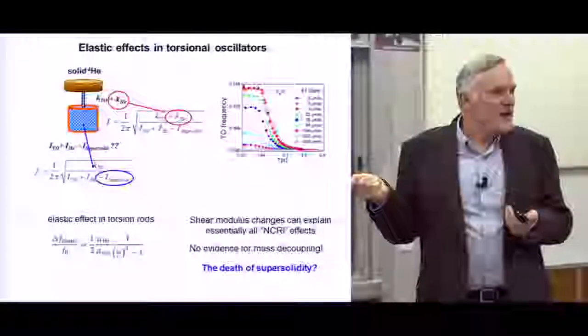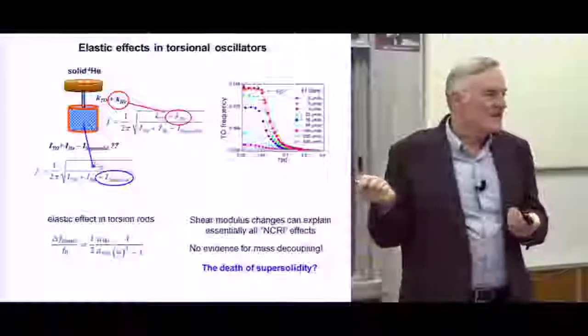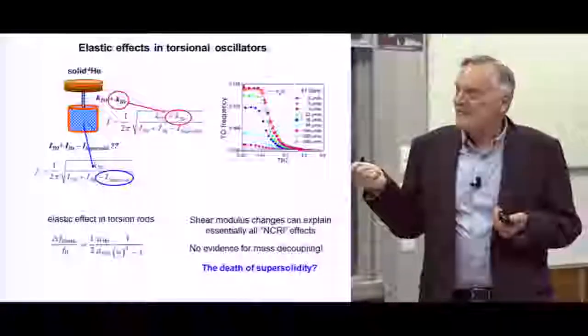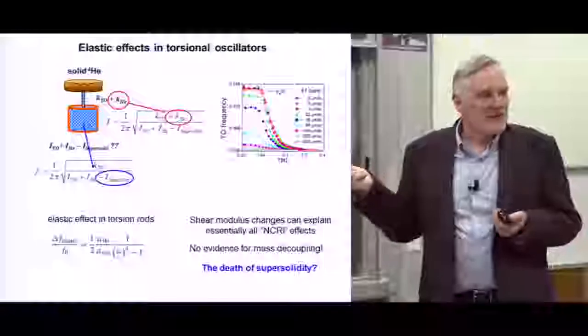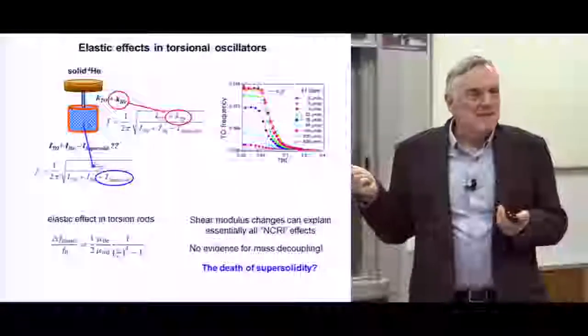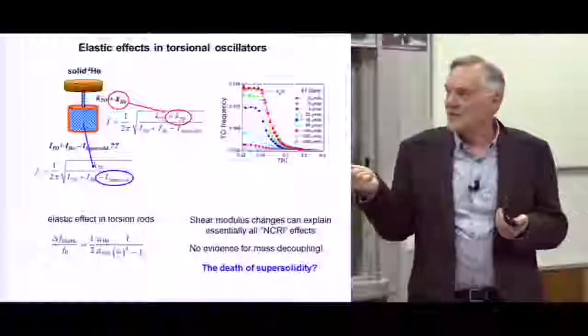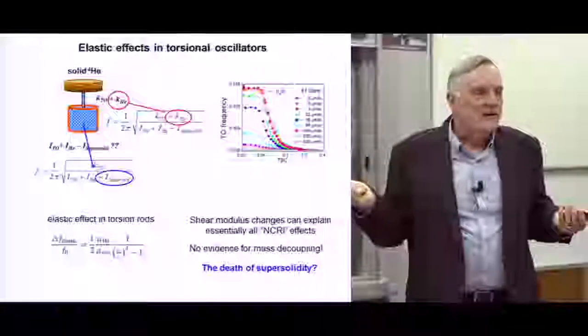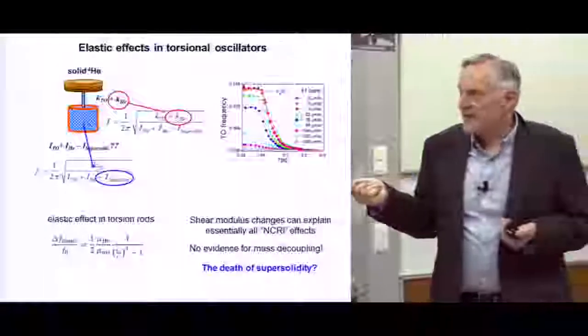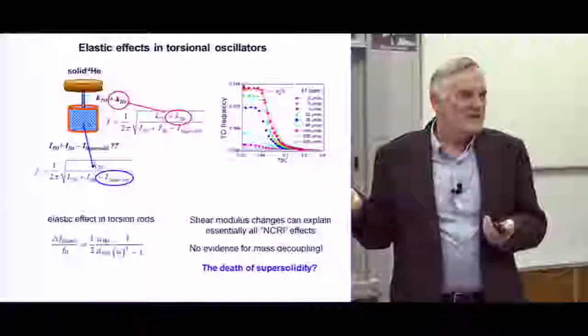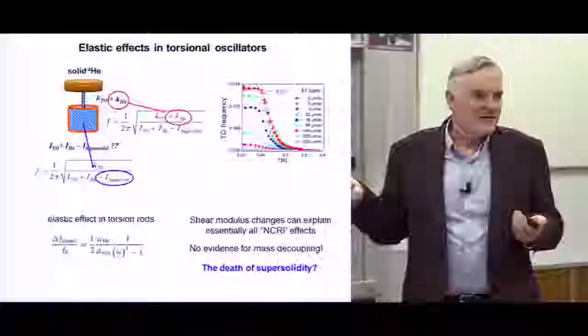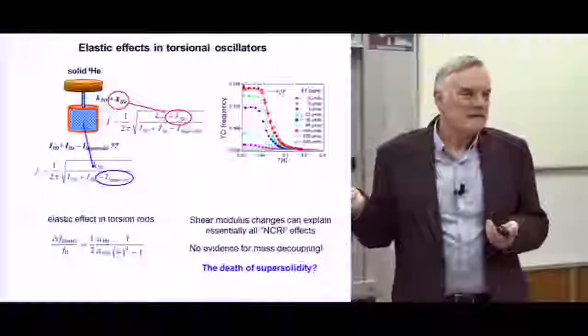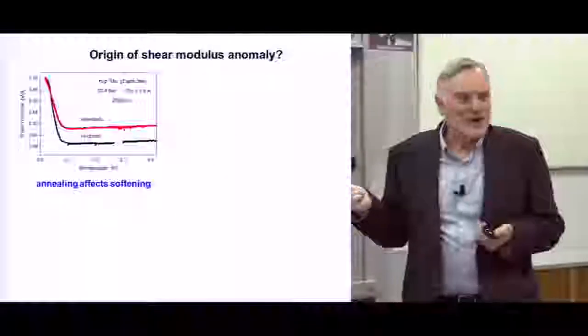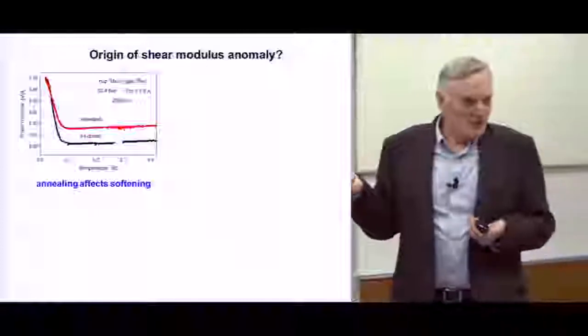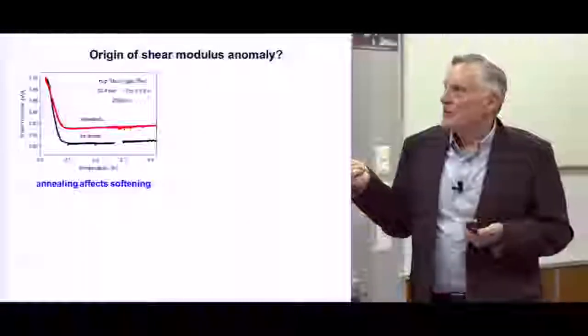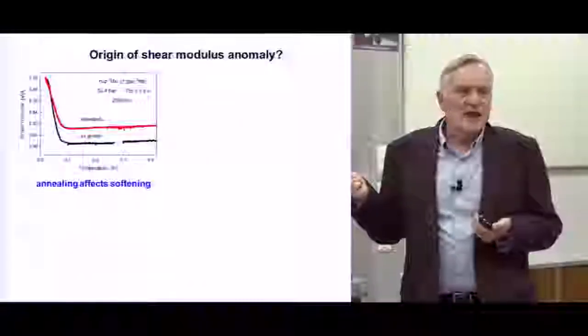And it stood up because there's no evidence left. Everybody that believed that they had a supersolid fraction and was skeptical of our argument went back, built a better torsional oscillator where it wasn't sensitive to elastic effects, and the effect went away. So the current state is there's no torsional oscillator evidence to suggest there's a supersolid. It's all gone. It's from about 2013. So what I'm going to focus on now, back on what really is true, which is real, is this shear modulus anomaly. This is very unusual behavior, right?